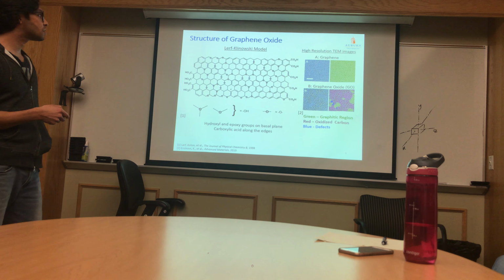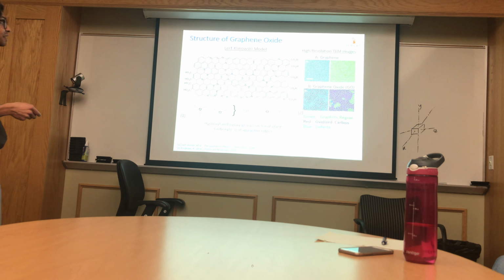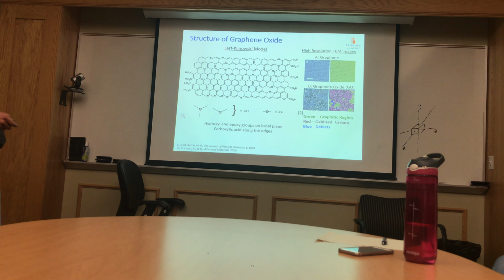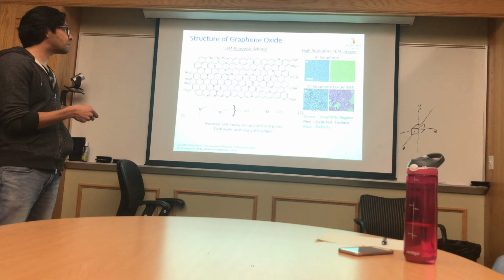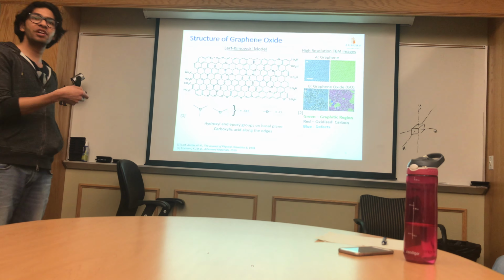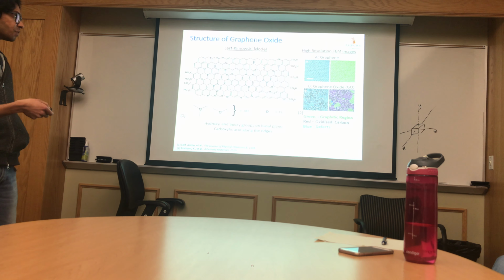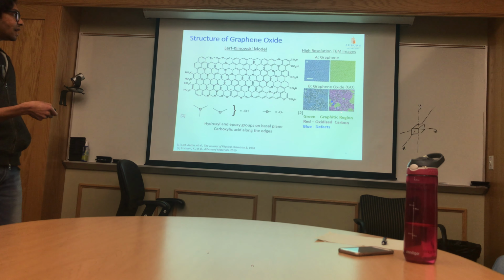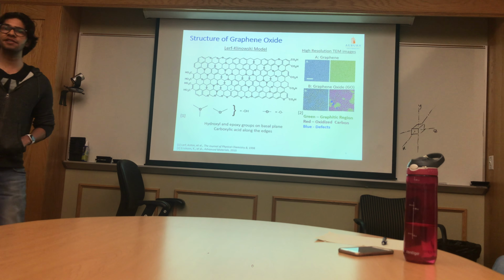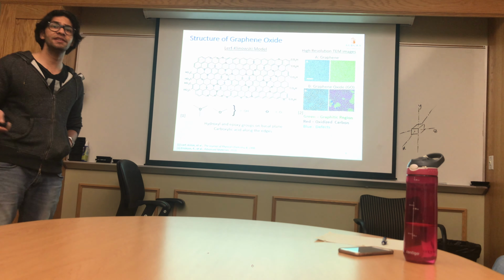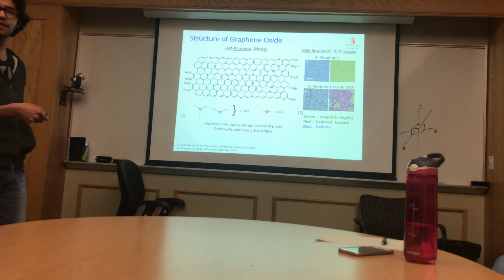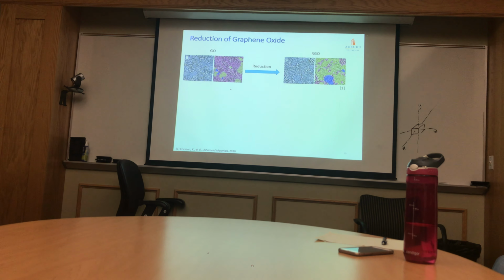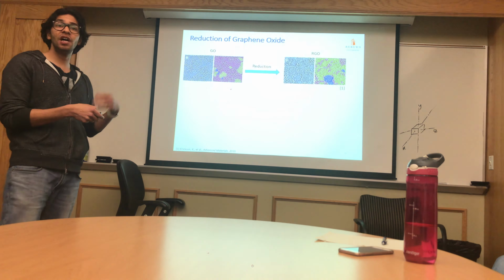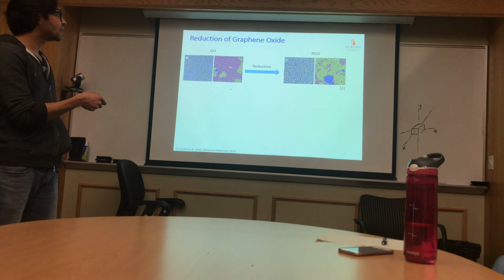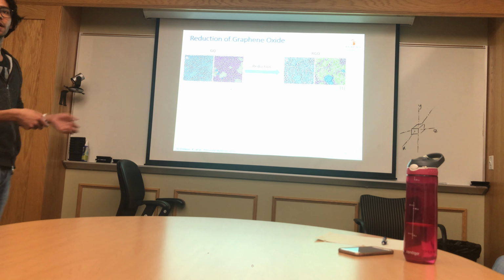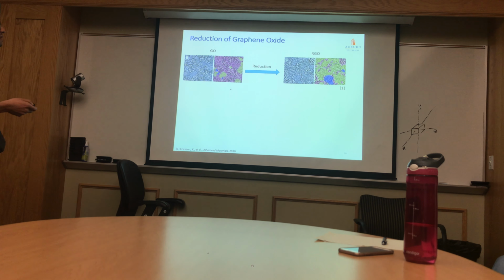Here I show the high resolution TEM images of graphene and graphene oxide. If you see, the green color represents the graphitic region. These are the carbons which are sp2 hybridized in nature and which are responsible for the electrical conductivity of graphene. If you see graphene oxide, most of the area is covered by red, which represents the oxidized carbon with oxygen functional groups, and it is sp3 hybridized, and hence it cannot conduct electricity. Now, of course, we need to do reduction to achieve the conductivity, and we can see these green islands have popped up in reduced graphene oxide, which suggests that this material is now conductive.